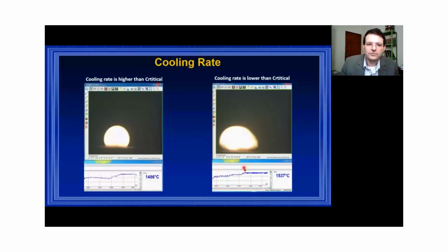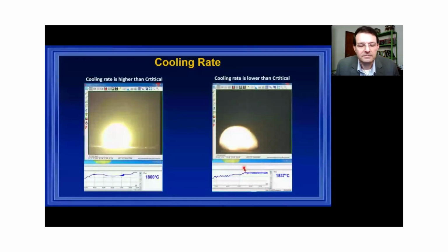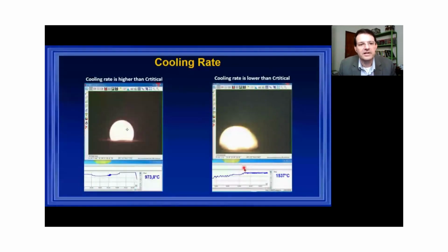And here we have two processes that I would like to show you. If the cooling rate is higher than the critical cooling rate, you have a glass. So this is an actual experiment, see, of a barium titanate silicate glass. We have a filter. We can remove the filter to see at low temperature. Now the laser is turned off. You have a glass there, so you can pick up the glass.